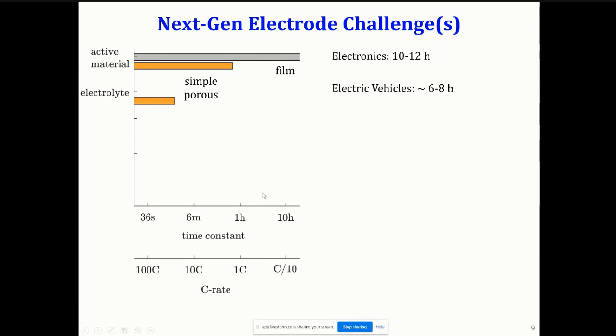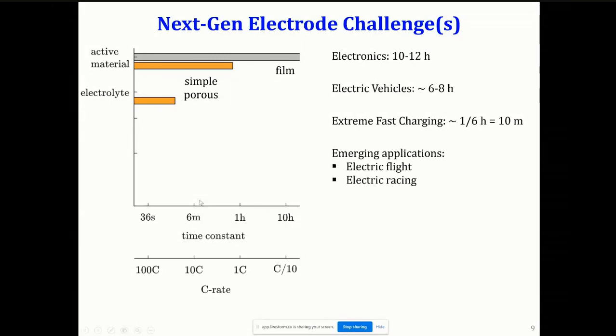Now, let's talk about one of the recent technologies, which is extreme fast charging. So now the goal is that we want to drive these vehicles for 6 to 8 hours, but we want to quickly recharge them, and we want to compete with the time it takes us to refuel a gasoline tank, right? And that sort of gets us back to 6 to 10C range, where we want to charge them pretty fast. Other applications which are emerging right now are electric flight, which would also increase the current at which you are discharging and charging. Electric racing will substantially increase the current you are discharging for certain spots in the lap.